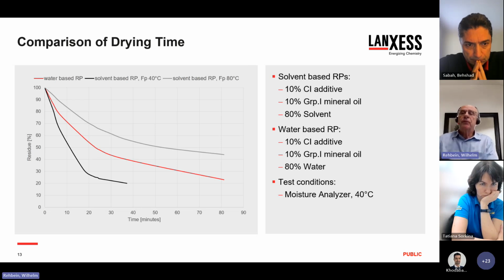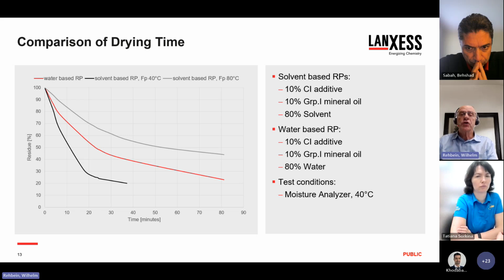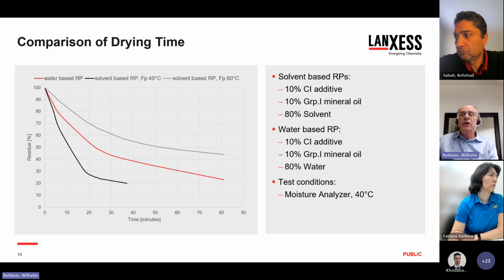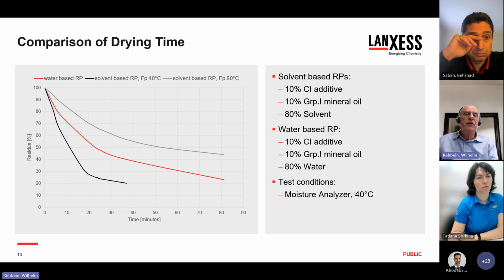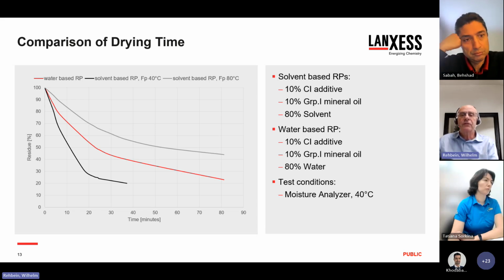Of course, the drying time of water is longer than the drying time of organic solvents that have a low flash point. However, we compared the drying time of solvent-based rust preventives with the drying time of the rust preventive emulsion that also contains some siccatives. Compared to a solvent-based rust preventive with a flash point of 40 degrees, this is the black line. The drying time of the water-based rust preventive, the red line, was, let's say, significantly longer. But on the other hand, there is the low flash point of the rust preventive, which causes a danger of ignition, just 40 degrees Celsius.